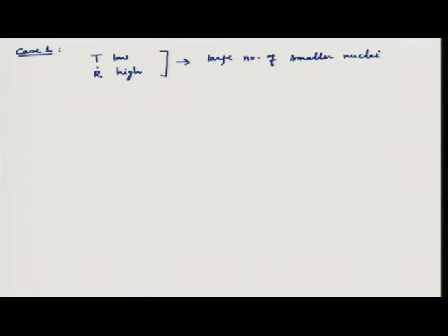Okay. So, large number of smaller nuclei. These will form in the initial phases and these nuclei will grow. In extreme cases, it will lead to polycrystalline material, because each nucleus will have a different crystal orientation, and will grow. So, the overall material will have a polycrystalline nature. In extreme cases, it will also lead to amorphous structure or amorphous material.